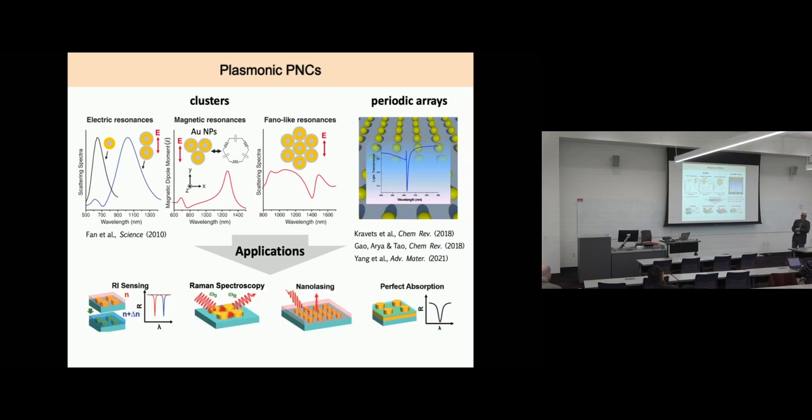And I told you Raman spectroscopy is one of them. With particles arranged very close to each other but not touching each other, you get extremely high electric fields in the region in between, which are called hotspots. And you can enhance Raman signals that you use for characterizing materials almost 1,000,000-fold, and even more, in fact. So that's one obvious application, and there are others also.